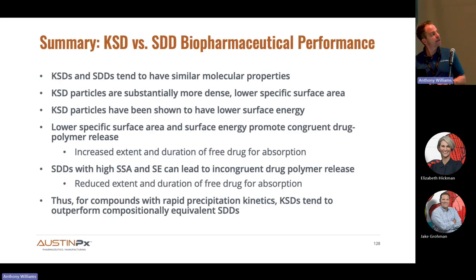Okay, so I think I've beaten you all over the head with all of these points, so I don't need to summarize, but basically it's just saying that molecularly, KinetiSol material and spray dry dispersions tend to have the same properties, but the particles are quite different. And I would argue that in most cases, a lower specific surface area and surface energy promotes better performance. And there's the line of honesty written there. For compounds with rapid precipitation kinetics, KSDs tend to outperform SDDs.